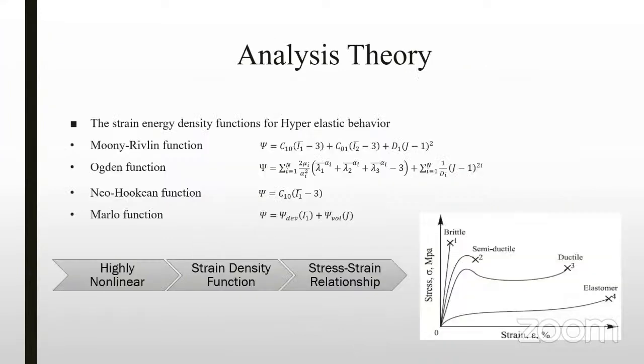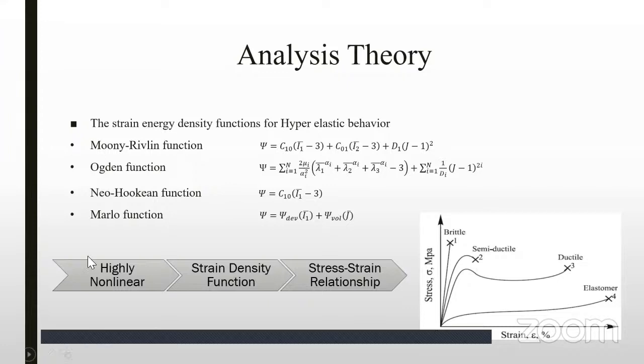To develop an analysis theory, at first we need to notice that the behavior of the elastomer is highly nonlinear in comparison with the other types of material, as we can see in this picture. So there is no direct relation between the stress and strain for these types of materials. So we need to use the strain energy density function to calculate the stress-strain relationship. These are some known strain energy density functions which are used mostly: the Mooney-Rivlin function, Ogden, Neo-Hookean, and Marlow function. The coefficients of these strain energy density functions should be calculated by doing some experimental tests. And these functions can simulate the hyperelastic behavior of the elastomers.